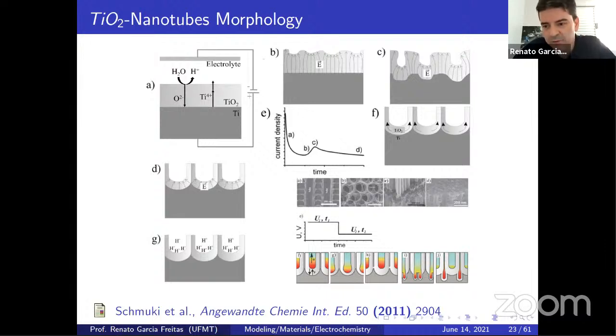a template for the battery or supercapacitor. In the dark, titanium oxide is a dielectric, isn't it? But if you put light on that, it's a semiconductor. So it's a very widely used kind of semiconductor. In Brazil we have several mines of titanium oxide, titanium indeed, the mineral. And the process to obtain titanium oxide is quite simple. If you put the titanium foil as the anode and platinum as the cathode here, and apply a voltage, suppose 40 volts, 60 volts. I mean, if you have 1 or 2 volts, we have an electric field strength up to 10⁹ volts per meter. So can you imagine applying 60 volts or 90 volts to obtain titanium oxide?